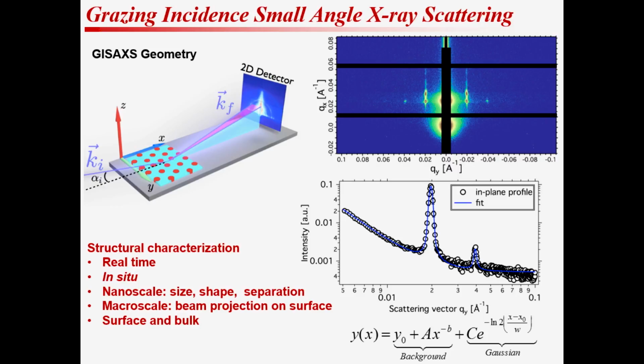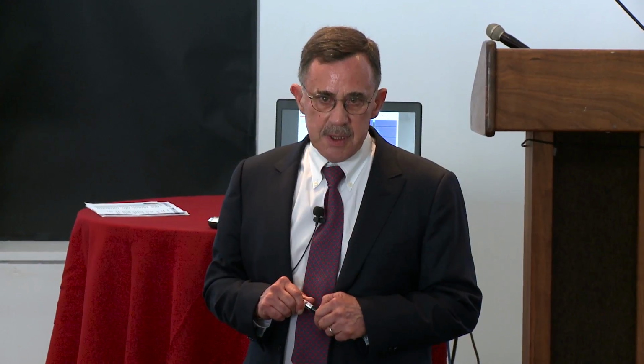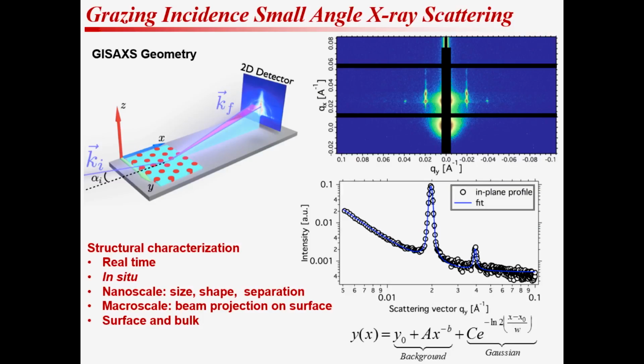Typically, substrates may be, let's say, an inch, 2-inch diameter, maybe more. And the elements that I have on the surface are nanometer in size. How can I characterize structures on the nanoscopic level over macroscopic distances? That's really hard to do. And the reason is that these elements are so small, I can take a scanning probe microscope and look at a micron by micron area. Now, if I have a substrate that happens to be 2-inch in diameter, how many microns is that? That's a whole bunch of microns. It'll take you forever to characterize it. So you need to have a technique that can characterize things over a large area on the nanoscopic level.